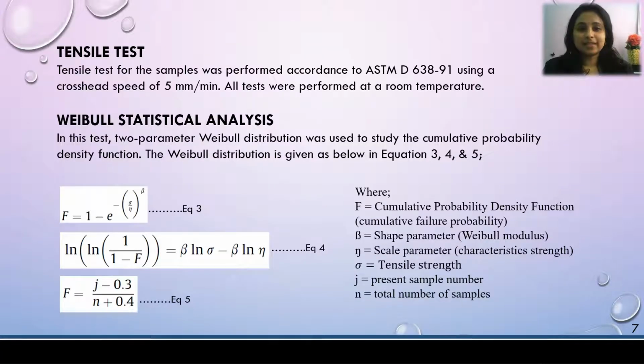Next up is the tensile test. Tensile test for the samples was performed according to ASTM standard using a crosshead speed of 5 mm per minute. All tests were performed at room temperature. On a side note, all these tests were done in the previous research and the raw data of this analysis were given to carry out the next step of my project, which is the Weibull statistical analysis.